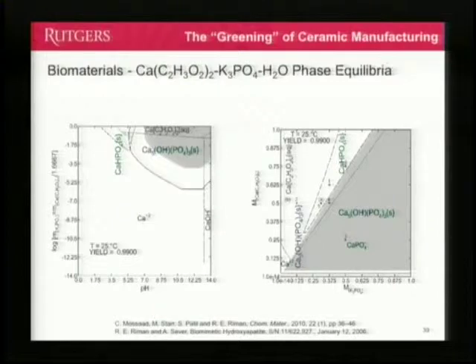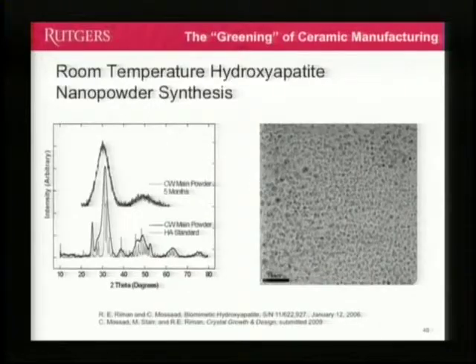And here's, again, she did the modeling, and the experiment showed that she could make a material that is some of the smallest particle size hydroxyapatite in the world. It's about 2 or 3 nanometers. The material is so unstable that if you let it sit for 5 months, it does something that ceramists think are unthinkable. You go from a crystalline material to being an amorphous material, because there's so much surface there. There's more atoms on the surface than there is in the bulk, so the whole thing just goes disordered, and the crystallite size actually decreases by a factor of 10.